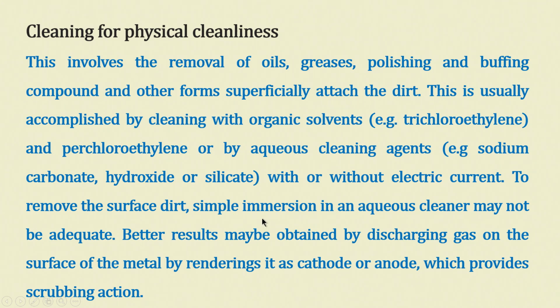To remove the surface dirt, simple immersion in aqueous cleaner may not be adequate at all. Just dip and taking it out is not very effective. Better results are obtained by bubbling a gas on the surface of the metal by rendering it as cathode or anode. That also provides very good scrubbing action. That means, we not only do the cleaning, but aid it mechanically by bubbling a gas. We can bubble air itself, does not matter.